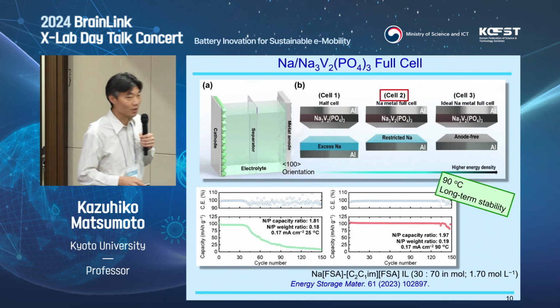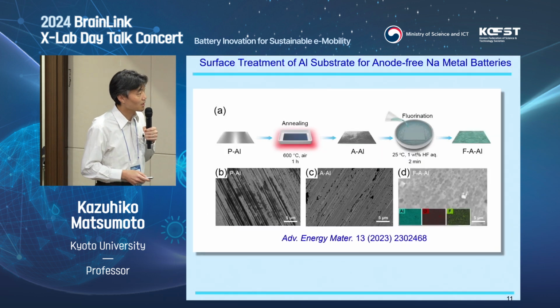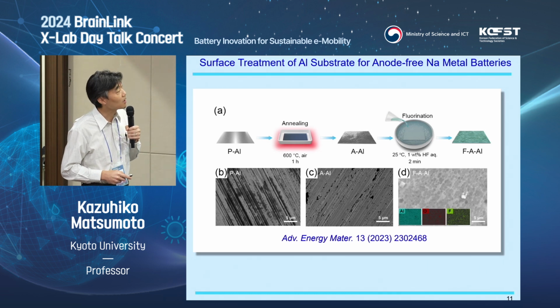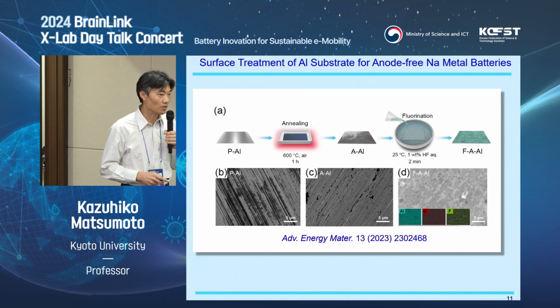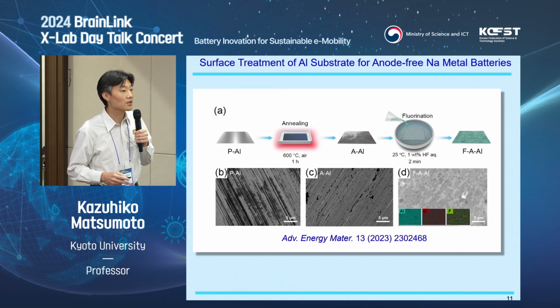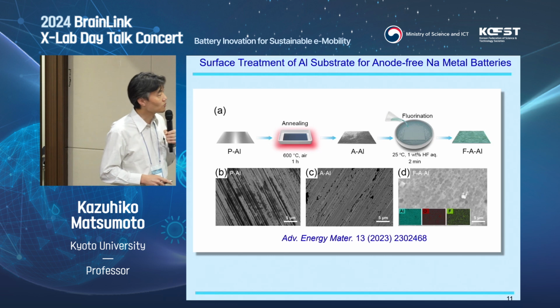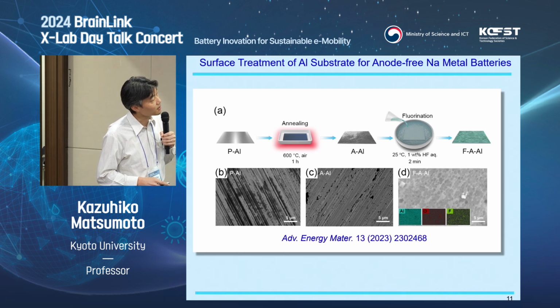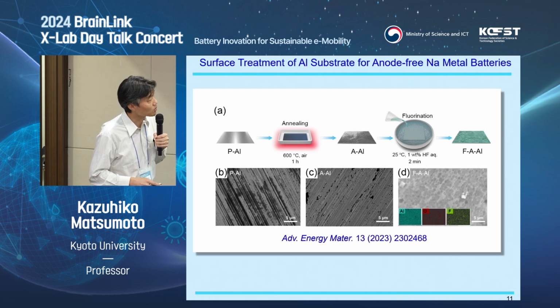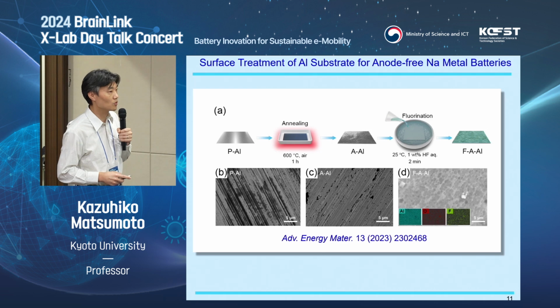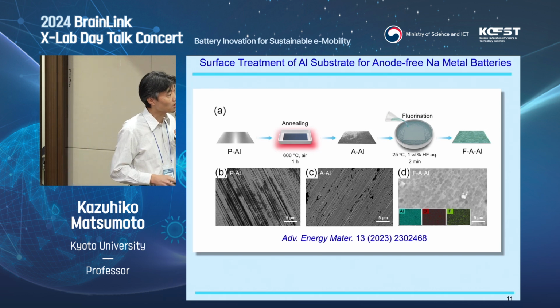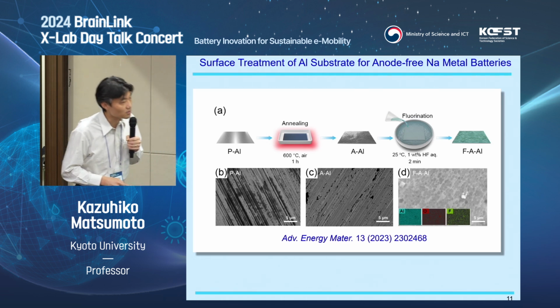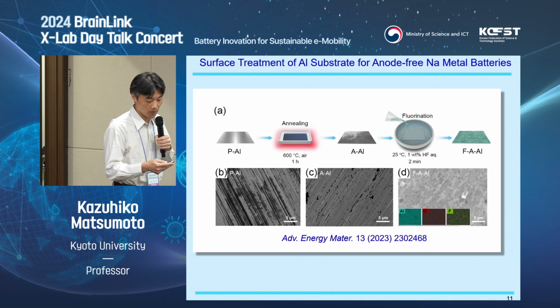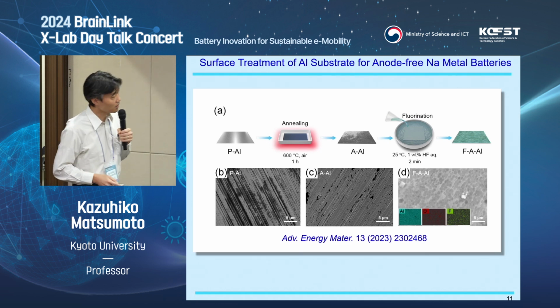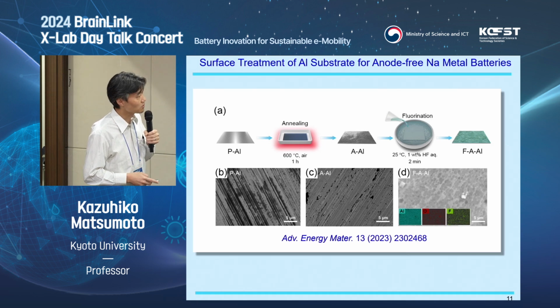Here, for the anode-free cell, I'm not talking about it a lot, but we also did some work on this, and I'm not showing performance because of time limitation, but just showing how to treat the surface of the aluminum substrate for this purpose. There are a lot of techniques known for the surface treatment of aluminum for sodium metal batteries, like carbon coating. But here we just treat it with high temperature annealing, and then we can control the crystal preferred orientation of aluminum to 100, and then fluorinate the surface with diluted hydrofluoric acid, which gives this surface morphology. And then by using this, we can really improve the performance of the anode-free cell. Details are in our recent publication.